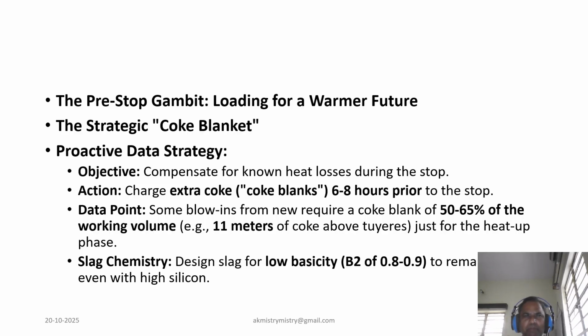Now, to combat this, operators have a secret weapon, a preemptive strike against the cold. We call it the pre-stop gambit: loading for a warmer future, the strategic coke blanket. This is a proactive, data-driven move. The objective is simple: compensate for the known massive heat losses during the stop. The action: charge extra coke, known as the coke blanket, into the furnace 6 to 8 hours before the plant shutdown.